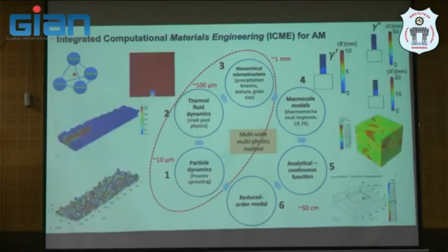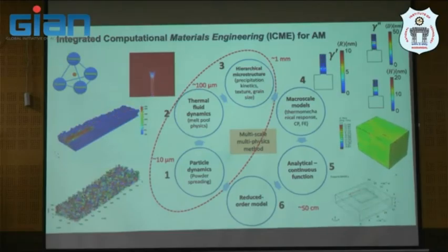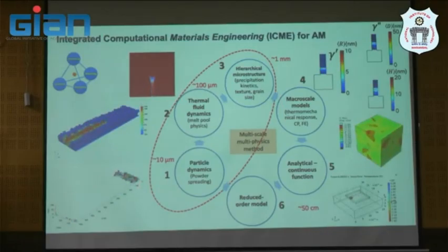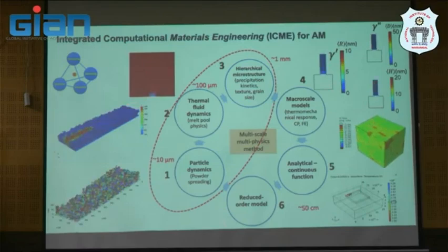So what we do, we try to use the computational framework to link this process, structure, and property relation, especially microstructure, and try to understand why it happened like that. And then from the aspect of microsegregation, elemental profile, and solute trapping, we believe that may link to the crack susceptibility. That is our hypothesis. And then we simulate this melt pool simulation of 3 nickel-based superalloys and try to link this to the property prediction later. So based on this, we talk about alloy design, we talk about process design. We want to design from microstructure design as well. So we link composition and process to microstructure development.